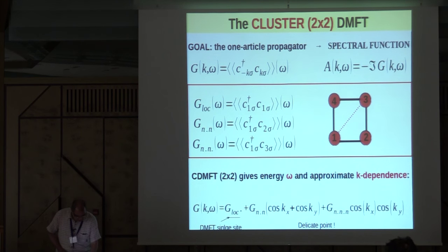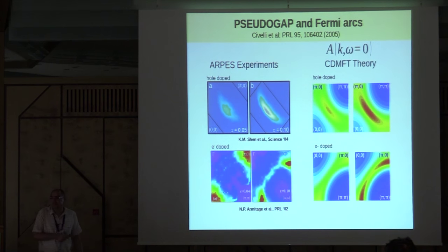All right. So I show you right away some results in the normal state. This is our prehistory of cluster DMFT. On the left, you have ARPES experiments from Shen and Armitage. This is a hole-doped cuprate, and this is an electron-doped cuprate. Again, this is a quadrant of the Brillouin zone, so you should have the full Fermi surface centered around the pi point. But the Fermi surface, at low doping, disappears, breaks into arcs. This is true in the hole-doped. Even in the electron-doped, the position of the arc is exchanged with respect to the hole-doped arc position, but this effect is still present. And if you do cluster dynamical mean field theory on the 2x2 plaquette, it doesn't matter then what you do to extract the G(k). In any case, you will get a strong modulation of spectral intensity and the formation of Fermi arcs, like in the experiments. So this was a first good result that was telling us that the method was giving some reasonable results.